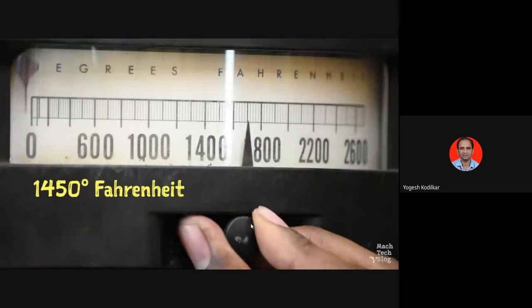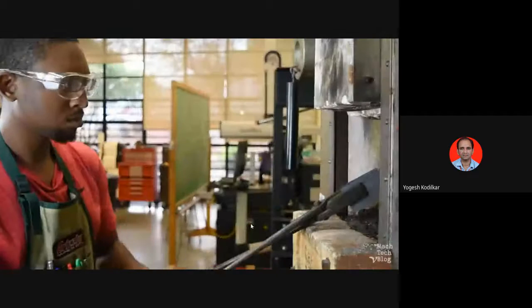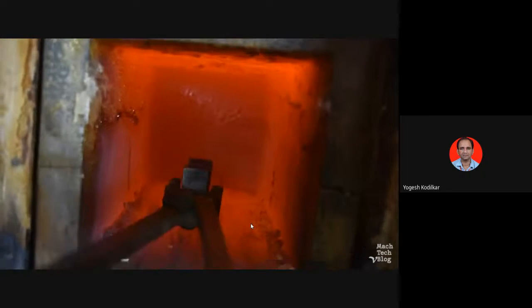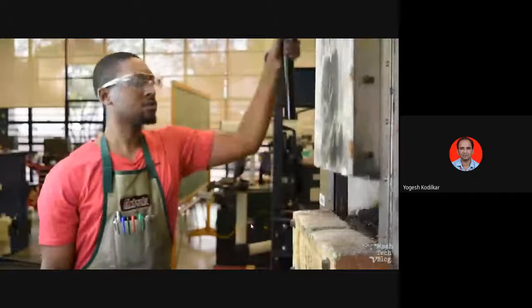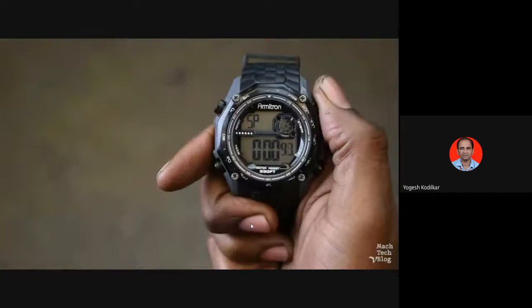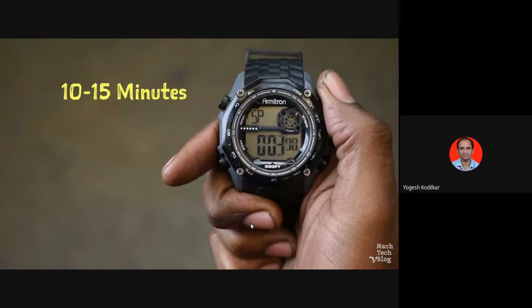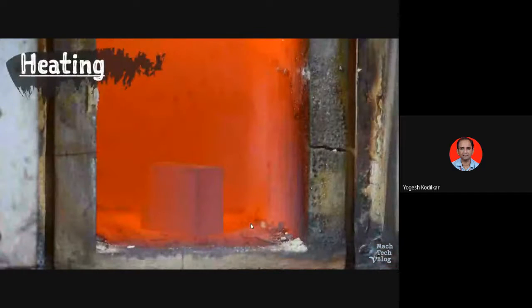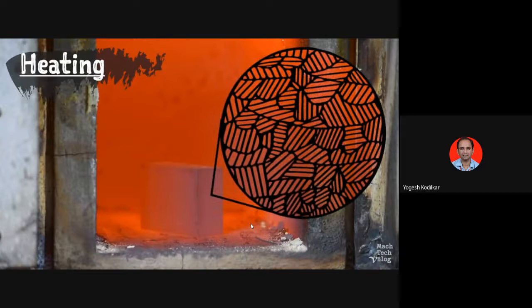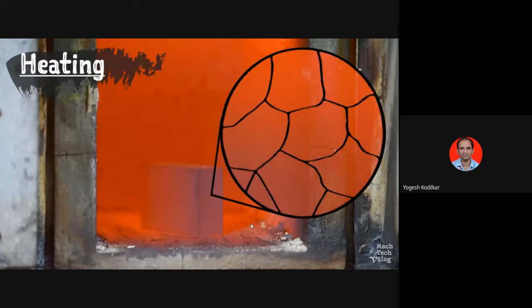Turn the heat up to 1450 degrees Fahrenheit, and then put the parts back into the furnace. We only need to get the parts up to temperature, so 10 to 15 minutes should do the trick. At room temperature, the microscopic structure of the high-carbon steel is composed of alternating layers of iron and brittle iron carbide. This microstructure is known as pearlite. When the steel gets hot enough, the pearlite dissolves, and the microstructure transforms into a non-magnetic solution of carbon and iron called austenite.